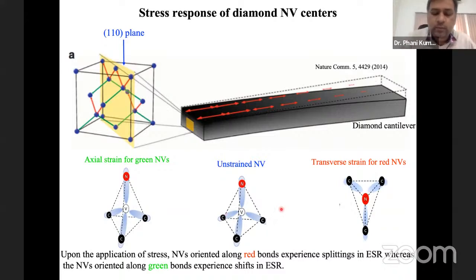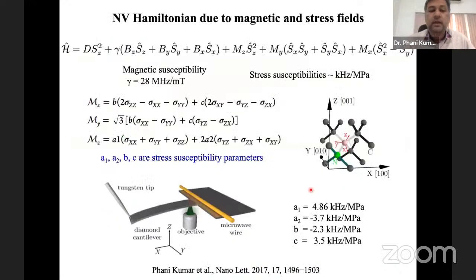Here also we can probe the response of the stress fields acting on the NV center. Because of the strain exerted on the NV center, as you can see in this 110 plane, the symmetry is broken. For the case of transverse strain, you see an elongation of bonds, and correspondingly we have this term in the Hamiltonian, which is given by these parameters mx, my, and mz. But unlike the electric field, stress is a tensor, so we have to describe it by 6 parameters.